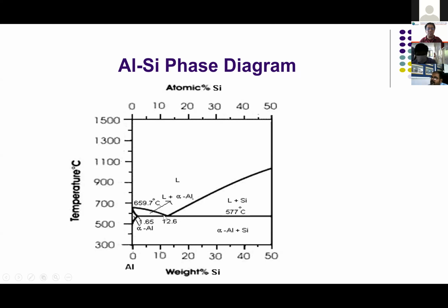Okay, so the eutectic point is the lowest point at which liquid can survive, and 1 degree below, that is 577, it becomes solid immediately. This eutectic point is the point at which the liquid becomes solid directly. So if you have a eutectic alloy, we call it a short range freezing alloy, where the casting shrinkage is also low, and it becomes solid directly.